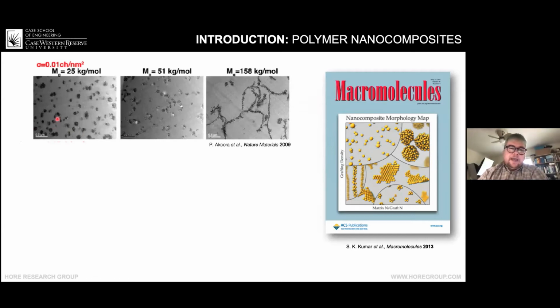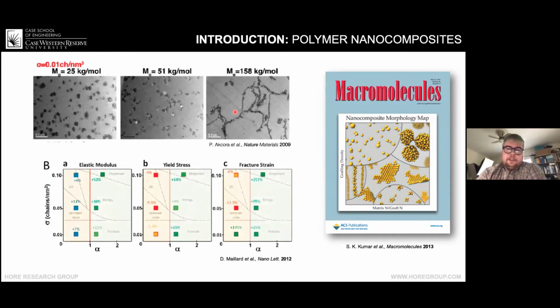And over 10 years ago now, these investigators noticed that when they had nanoparticles, these were silica grafted with polystyrene, and they put them inside of a polystyrene film, they got different structures depending on the molecular weights of the polymers that were involved. So this was interesting just from a pure polymer physics standpoint, but it also has real implications in terms of the mechanical properties of the material. So you can see here that the morphology, whether it's strings, kind of like up here, dispersed or fractal-like structures, jammed states, these significantly affect the fracture strain of the material.